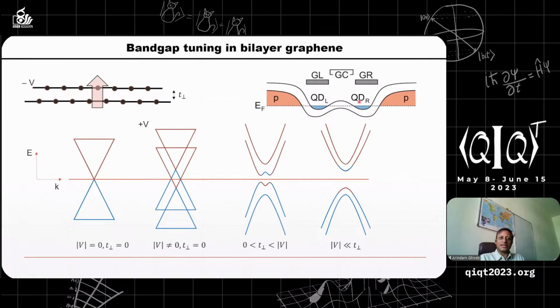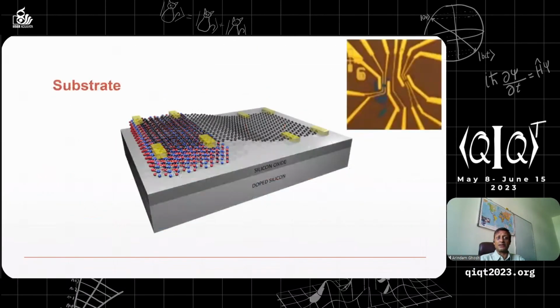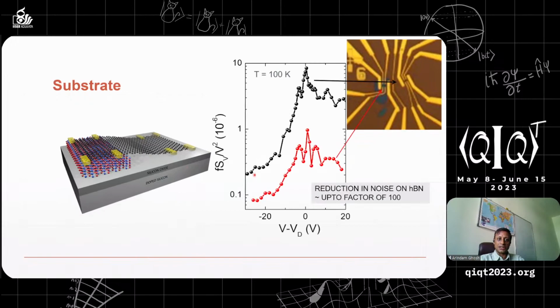So naturally, if you want such systems to come into quantum processing, you need to know what their noise is. We have been measuring noise in these systems. We find the substrate on which you keep it is extremely important, and this is why often you encapsulate graphene in boron nitride kind of insulating substrates. You can see the noise magnitude is extremely large when the graphene is kept on amorphous substrates like silicon oxide, but the noise comes down dramatically if they are kept on the boron nitride kind of substrate.